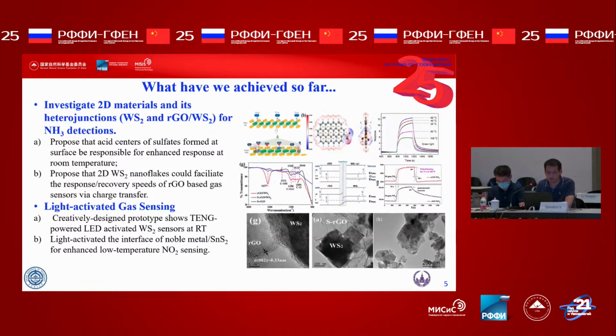What we have achieved so far: we have investigated two-dimensional nanostructures and their heterojunctions for ammonia detection. We propose for the first time that the acid centers of sulfates formed on the surface are responsible for the enhanced gas sensing. And we also propose that the two-dimensional tungsten sulfide nanoflakes, incorporated in the RGO, could facilitate the response and recovery speeds of the RGO-based sensors for room temperature ammonia detection. The mechanism involves charge transfer at this interface.